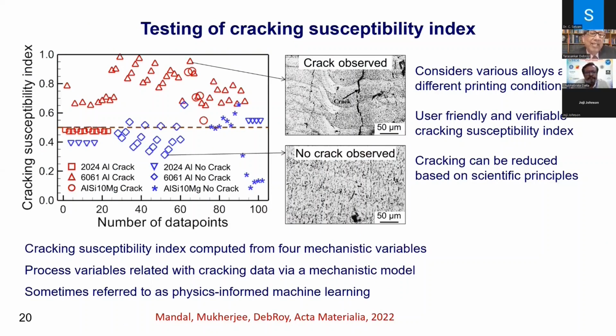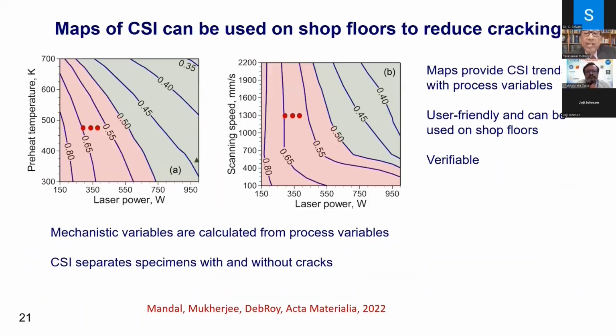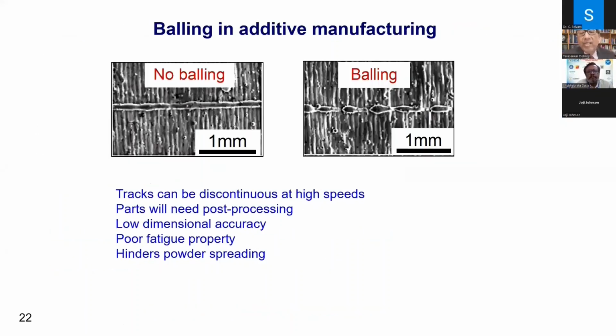And you can validate it by developing a cracking susceptibility index for data that you can collect from the literature, and you can show that when the susceptibility values are greater than 0.5, your chance of getting a crack in your sample is much higher than otherwise. You can also develop maps. Here we are plotting scanning speed versus laser power, or preheat temperature versus laser power, and these are profiles of the crack susceptibility index, so you can see whether you are in the safe region or you are vulnerable. You can also prevent balling defects that occur when you go too fast.